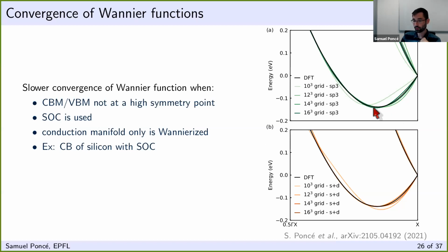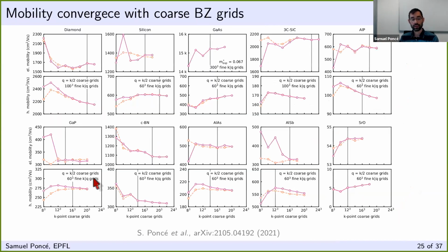And therefore, it's difficult for the Wannier function to find, for example, the minimum. So you can see that this minimum oscillates, and you need to go to quite a dense grid in order to converge the result and re-obtain the DFPT result. And so this is the main reason why the mobility converges relatively slowly with the k-point grid density.